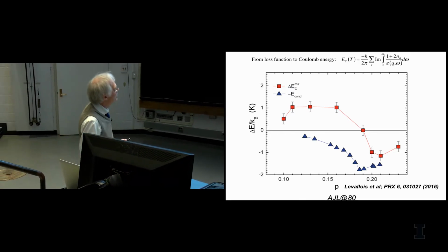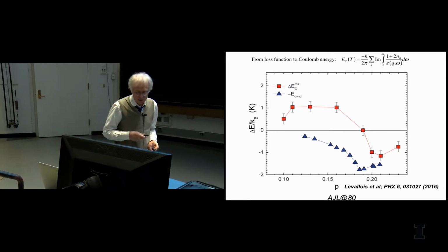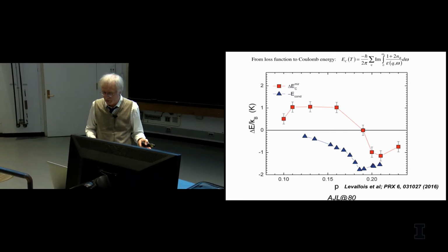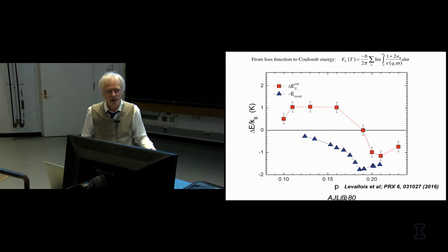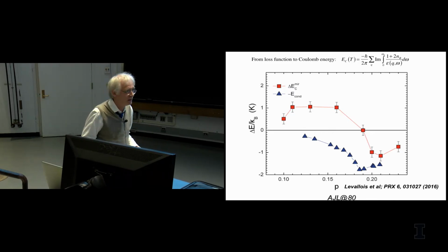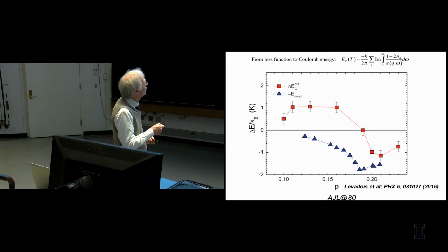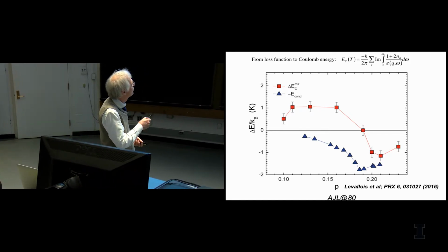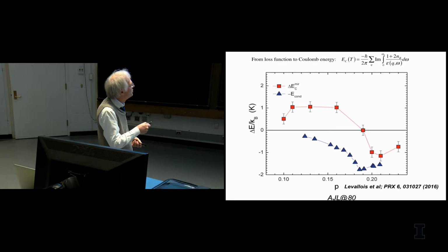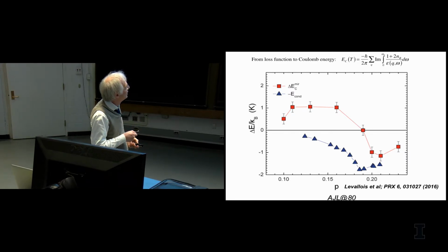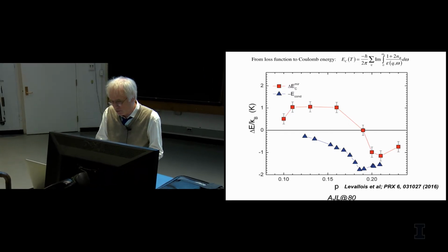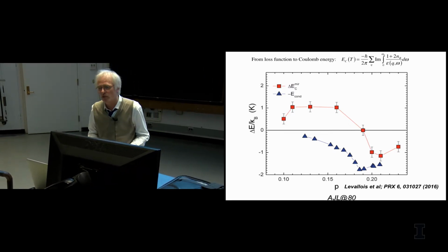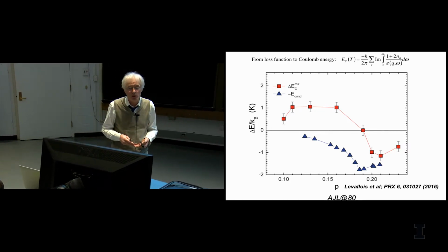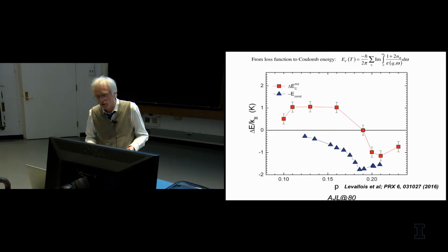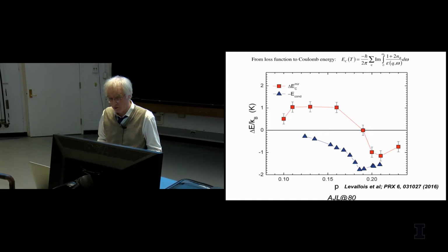So we have been floating around various kinds of ideas why this is increasing over here. One possibility would be that on the underdoped side, you already have pairs in the normal state, and it's those pairs that condense. And then there is no simple way to predict what this Coulomb energy would do. So this could be different from what you see on the overdoped side. Then, of course, you could argue that, okay, we only looked at Q equals 0. You really would have to look at much higher momentum values, maybe at the zone boundary or maybe even beyond. And for that, one needs to work with different kinds of techniques than we actually have applied.